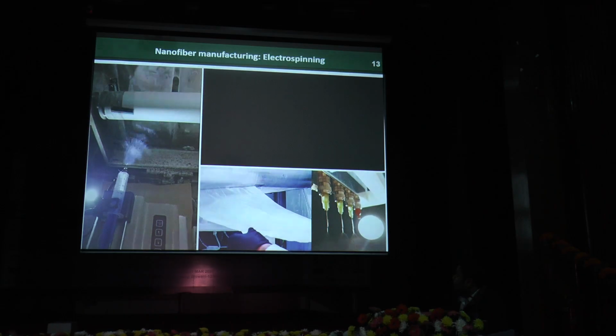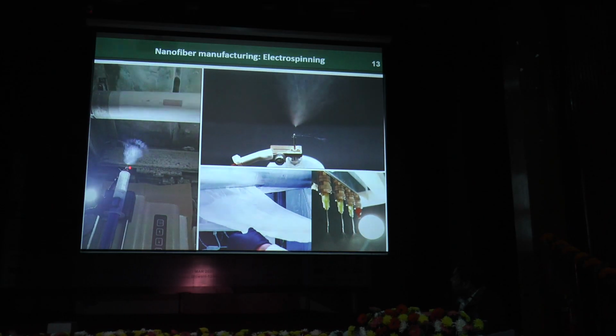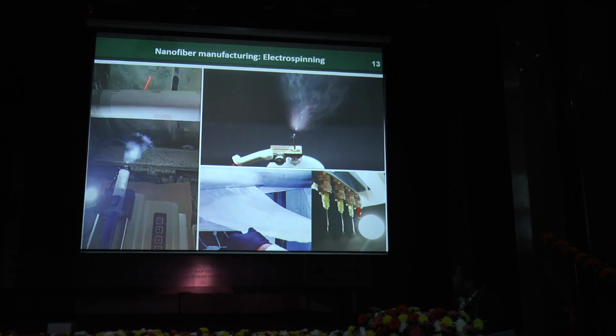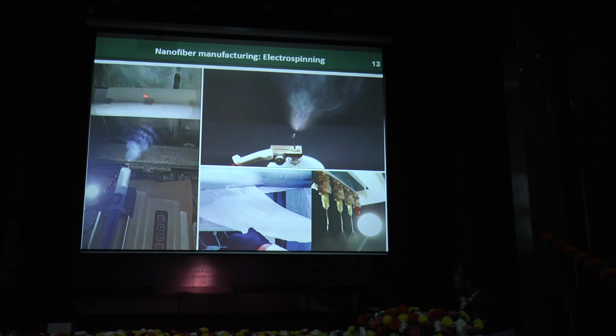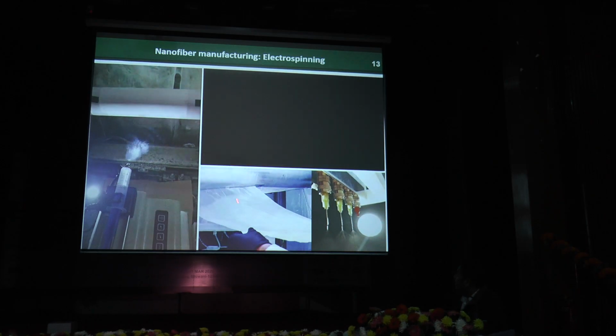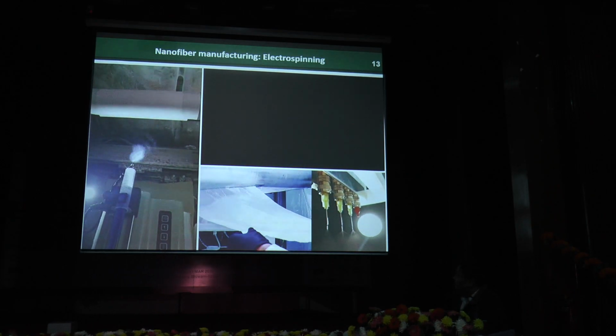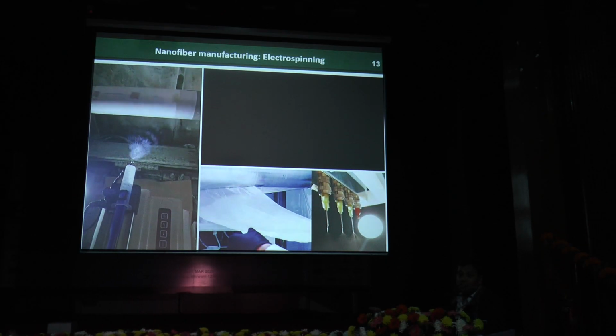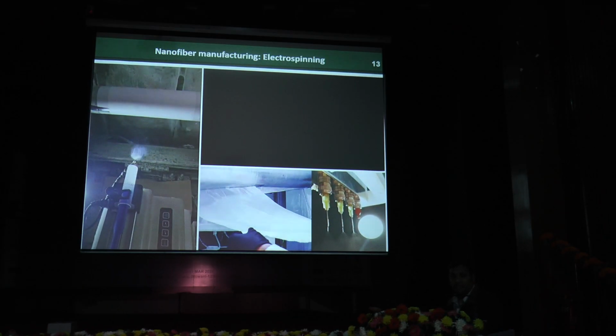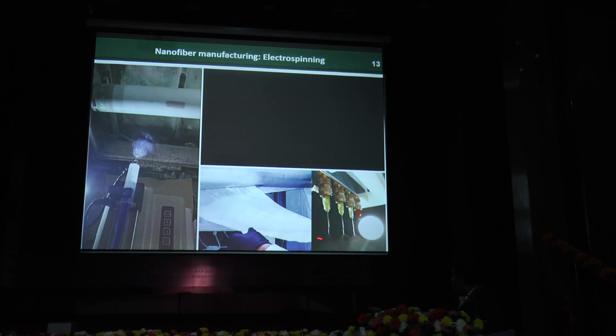So this is the instrument, a laboratory scale single nozzle instrument. When you apply sufficient high voltage to the polymer solution, you can get the nanofibers. And this is the rotating collector. You can collect the nanofiber, and you can see it here. After collecting, the nanofiber is in a membrane-like form. And this is laboratory scale. We have only one nozzle. We also have a multi-nozzle electrospinning machine. Actually, we developed this machine. We designed it in our institute, and we have the mass production machine. This is the multi-nozzle electrospinning machine.